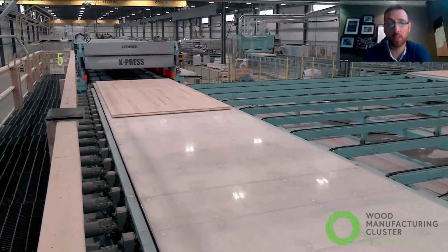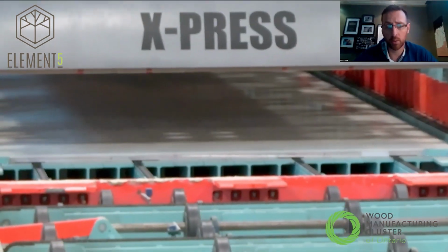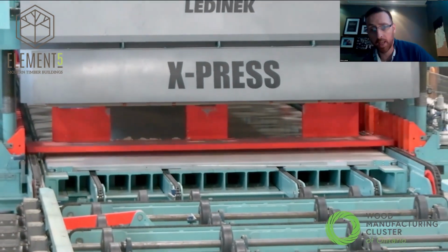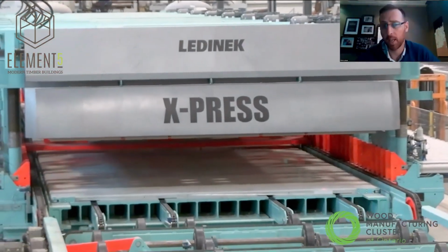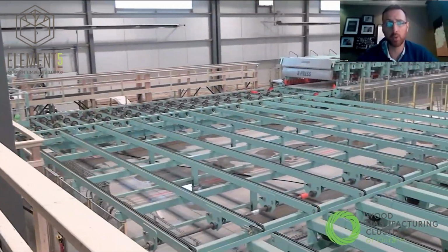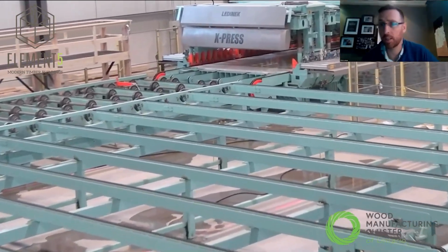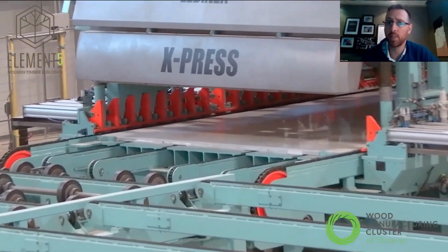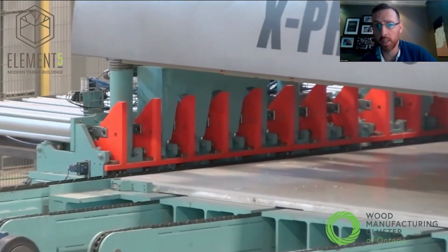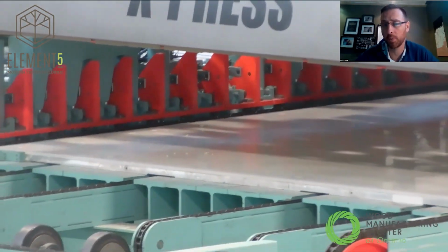This is the X-Press technology. This is another patented technology from Ledinek. So the panel is loaded in on the actual platen, which lowers. They have a servo force rail that brings in and clamps the end to get its pressure. Then the sides come in for a specific pressure, and then the servos lower the entire overhead section. It's in 8 specific platens, and the platens that you're using lower down, and then airbags go off to get to 220 psi, and it sits at that pressure for 2.5 times whatever your open time of your adhesive was.